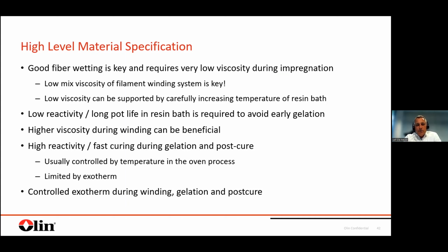In the end, for the wet winding process, low reactivity or long pot life in the resin bath is another important requirement in order to avoid early gelation, which would cause the need to have regular clean out of the entire resin bath, and so limiting the productivity and causing waste at the same point of time. So long pot life is the second important thing.